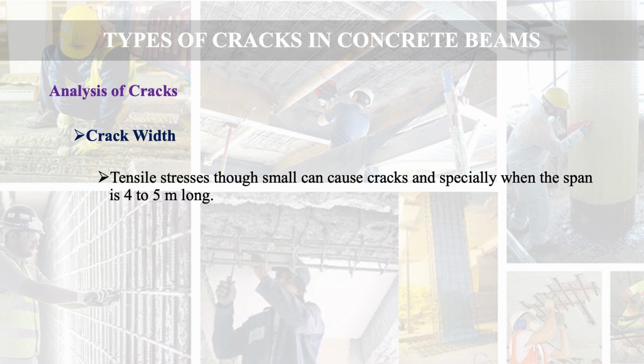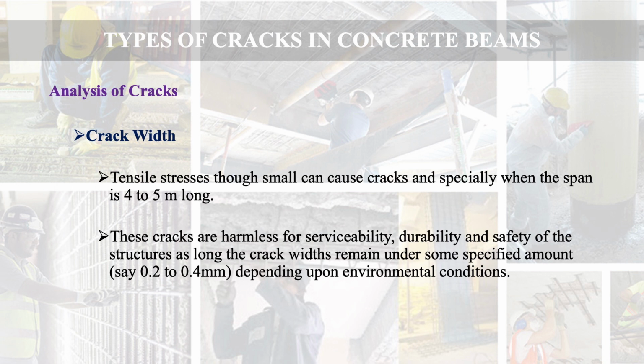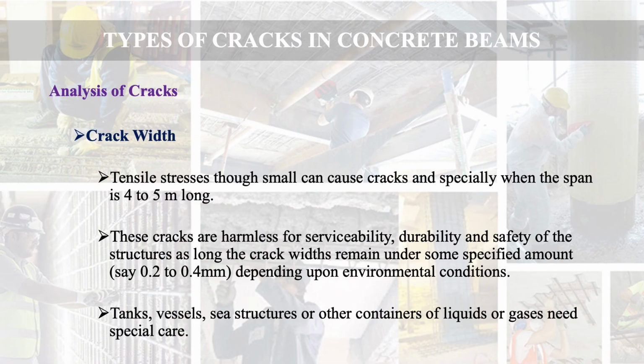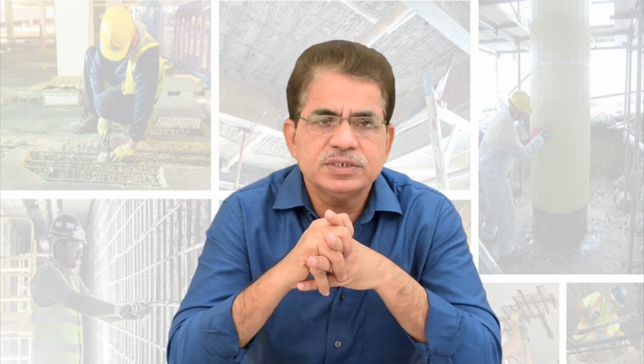The tensile stresses, though small, can cause cracks, especially when the span is 4 to 5 meters long. These cracks are harmless for serviceability, durability and safety of the structures as long as the crack width remains under a specified amount, say 0.2 to 0.4 mm, depending upon environmental conditions. This factor is very important, because if environmental conditions are different, then a small crack width may actually be very detrimental. Tanks, vessels, sea structures or other containers of liquids or gases need special care because there should not be any leakage due to cracks.